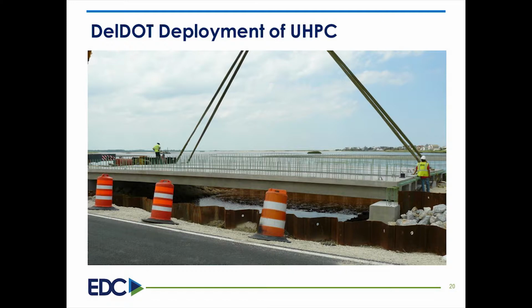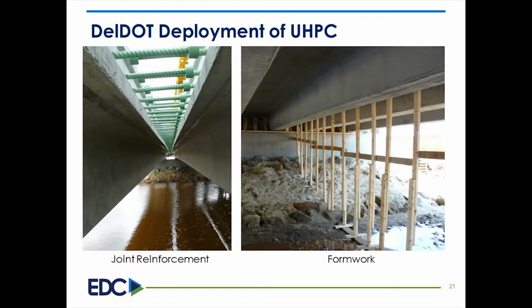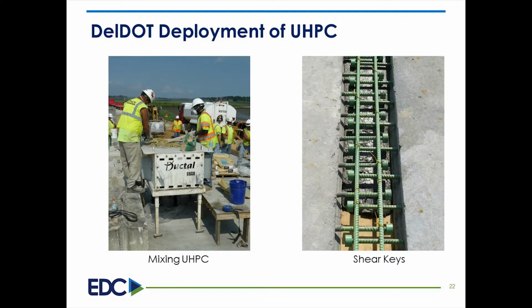But here's the beams going in. See, they put them in pretty quickly. He formed it up on the bottom. He had it dried up and just used forms and jammed them up in there. He did do the top forming. And I like that picture. One of the issues they had was the mixer was small, and they couldn't mix as fast as he could place it. So that was kind of the driving point for here.